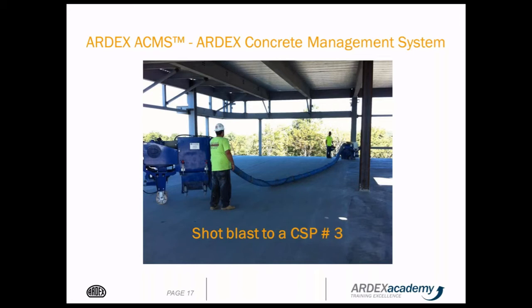And the beauty of shot blasting in this phase of the concrete is your output. Looking at this shot blaster here, for example, it was a 20-inch width, and they did about 14,000 square feet in roughly 3.5 to 4 hours.